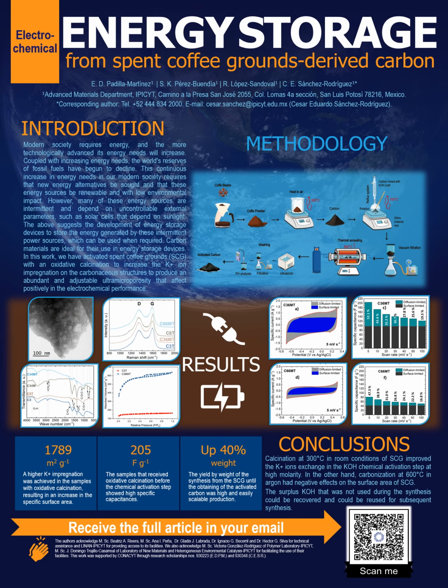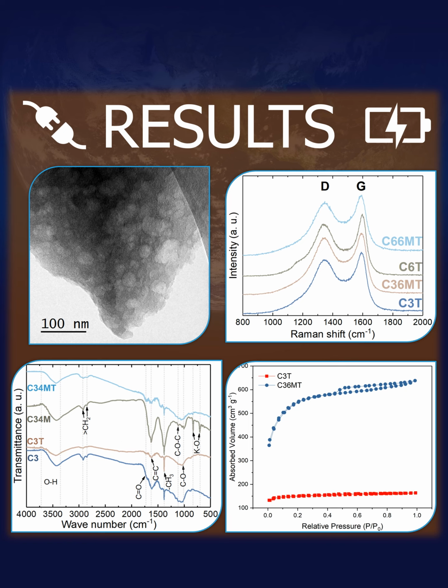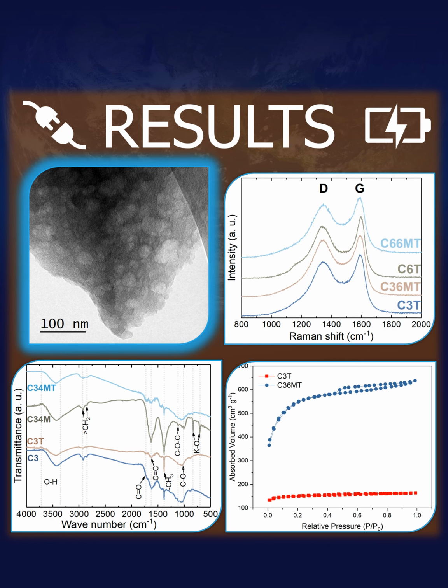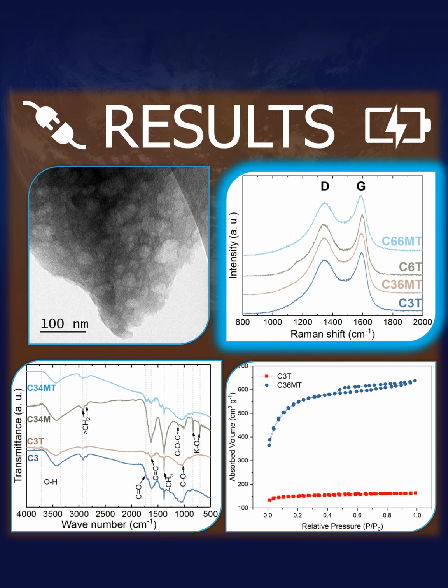Now moving on to the most relevant results, we get a high pore size distribution with the formation of this kind of craters, as we can see in this TEM micrograph. The presence of the peaks D and G in the Raman spectroscopy indicates a good graphitization. This tells us that our materials have a good electrical conductivity.